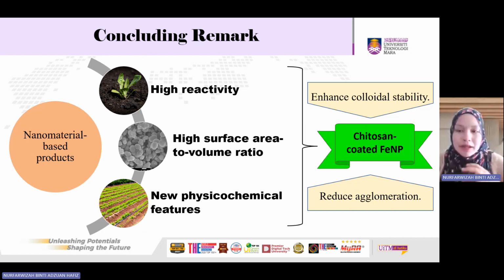However, the aggregation of the particles in biological and physiological conditions presents a problem when using only iron oxide in seed priming. The introduction of a less toxic biopolymer that can hold the iron oxide nanoparticle in a lower cluster size over a long term can be used for surface functionalized nanoparticle. Thus, to conclude this review paper, we can, as far as known, reduce the agglomeration of iron particles during the manufacturing process when surface modification of the nanoparticle is applied by using chitosan.